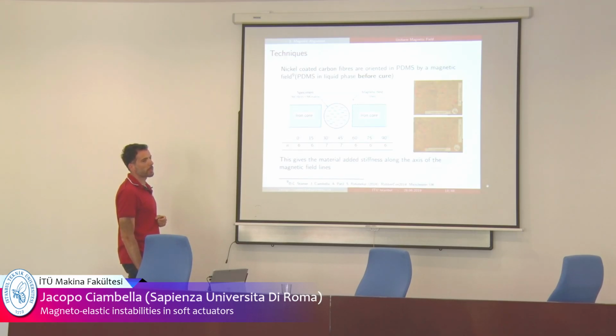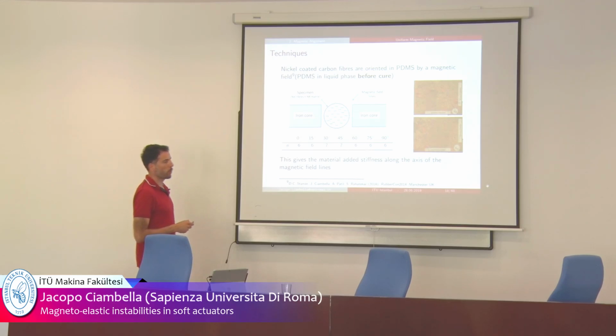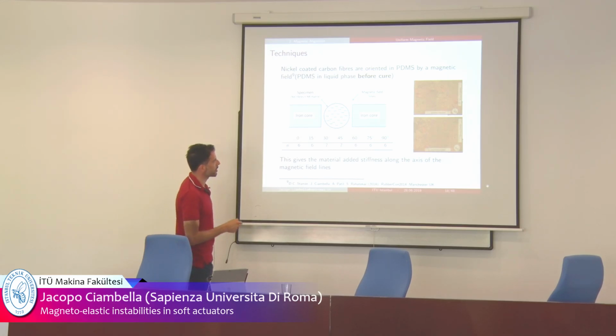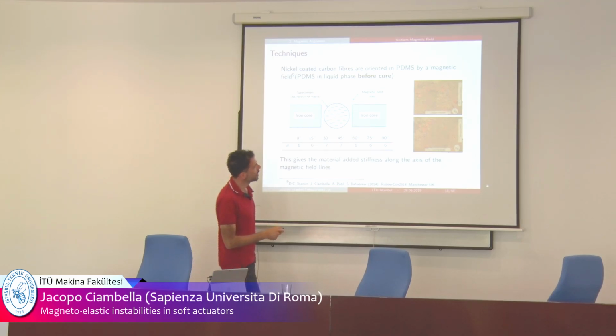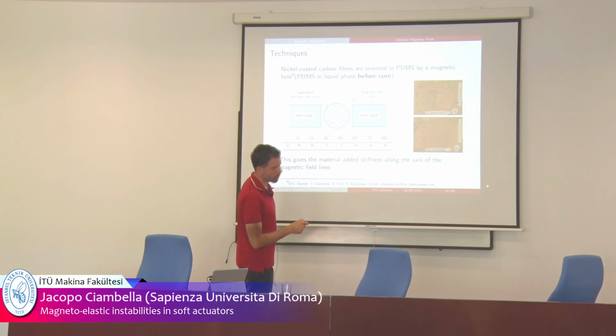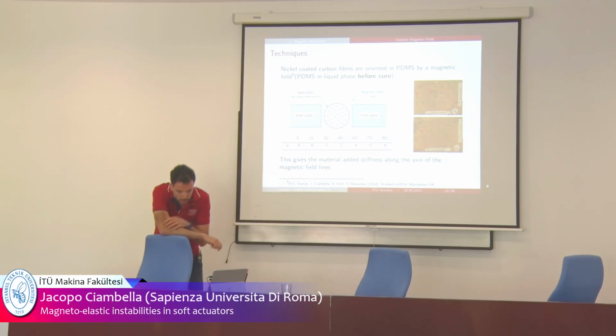How did we get the orientation? We used electromagnets. We poured the solution of PDMS and fiber within the plates of the electromagnets. We turned on the electromagnets and the particles were oriented. And we manufactured specimens with different orientations from 0 to 90 degrees. Okay, this is an example where the fibers are aligned. You can't see very well, but there are red fibers which are aligned pretty much.